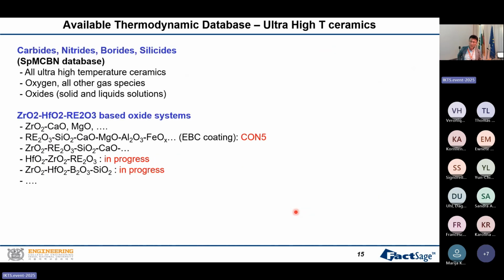Sorry. And because this is not only for refractory, I say ultra high temperature ceramic material. From my point of view, ultra high temperature ceramic material is also refractory material under that extreme environment. Okay, so for them, they are typically using carbide, nitride, and all this high temperature material. And we also have those kinds of databases. And also for carbide, nitride and boride, when it goes to extremely high temperature under oxidation condition, now everything is oxidized. So it means you're back to the oxide again. So we have to know all these oxide components simultaneously.